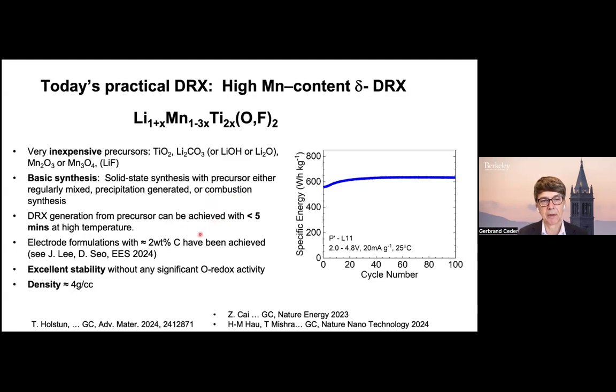They have certain advantages. You can make these materials in 5 minutes at high temperature. So they can, in principle, have particularly high throughput on the synthesis. If your precursors are well mixed, these materials only need to spend about 3 to 5 minutes at elevated temperature to make the DRX. They have excellent stability, and that's in part because the top of charge is only manganese 4, which is a stable redox state, as I showed you before. Manganese 4 is stable in air. And they have virtually no oxygen redox activity, unlike, say, the early DRXs.